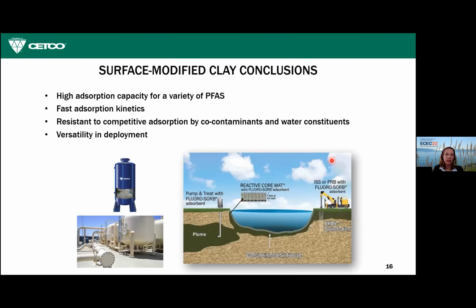So, conclusions. Surface modified clay, the key things to remember: it has a high adsorption capacity for a variety of PFAS and is specific for PFAS. The adsorption kinetics are fast. You can use a 2-minute empty bed contact time if you're looking at drinking water filtration. It's resistant to competitive adsorption by co-contaminants, and it's very versatile in its deployment.